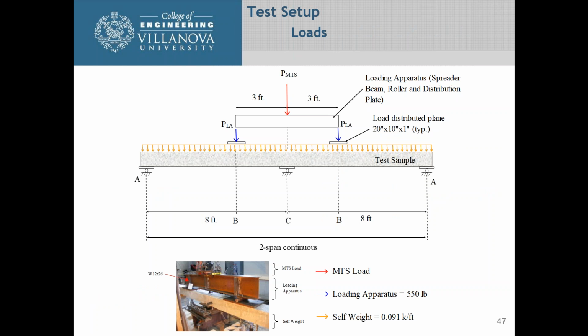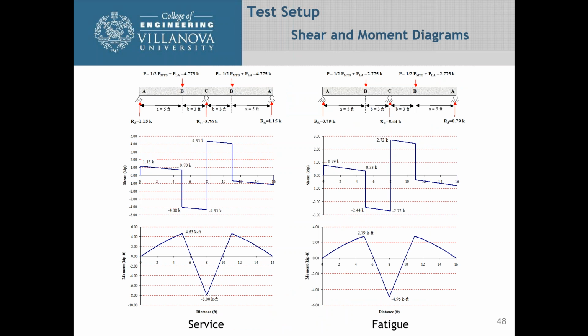So this is the loads that we had. We had your uniform distributed weight of the beam, and that ended up being like 91 pounds per foot. We also had to take into account the loading apparatus, which was about 550 pounds, and put all that into our equations to figure out what our shear and moment diagrams are going to be under service and fatigue. And what you have here is what the 2 different diagrams are.